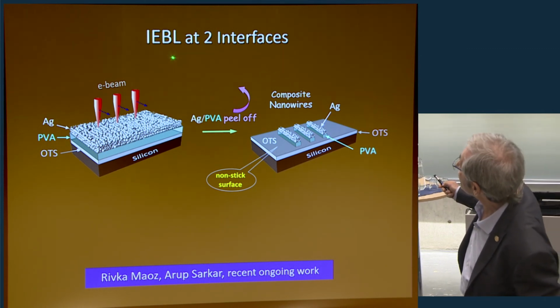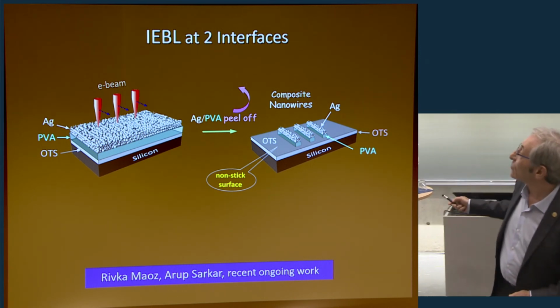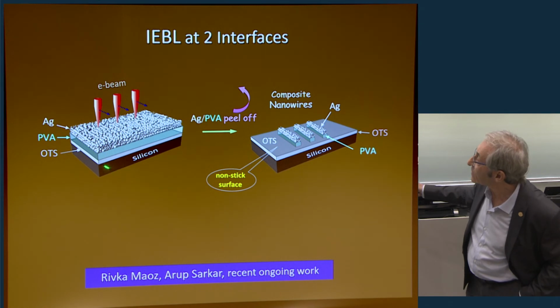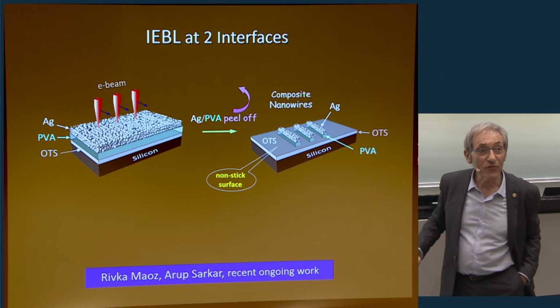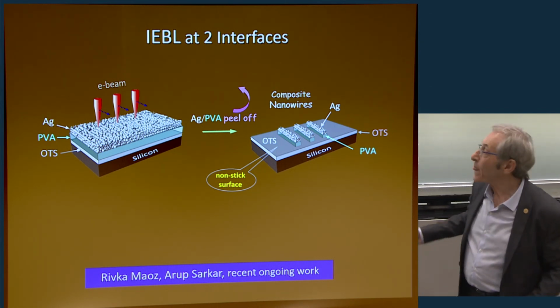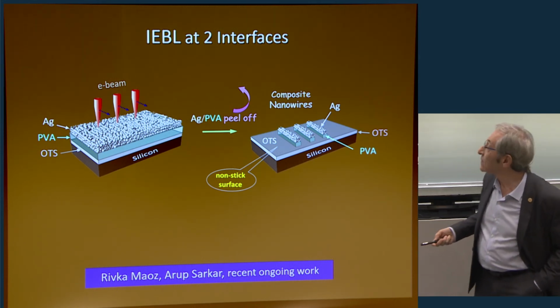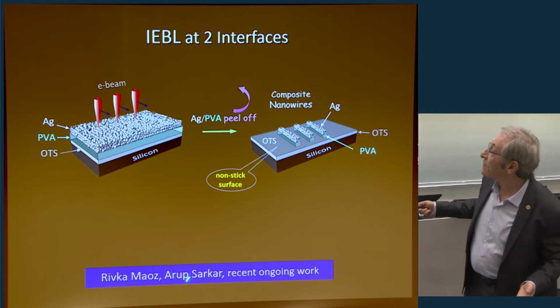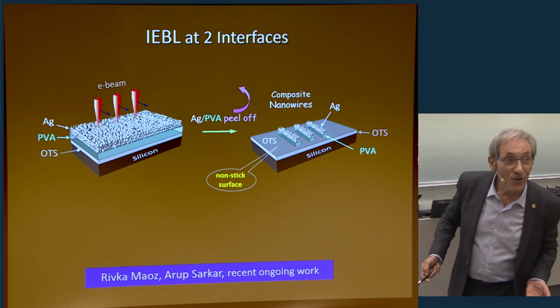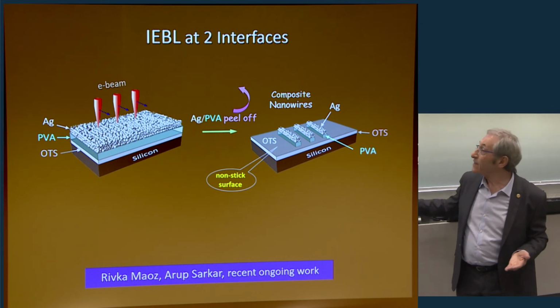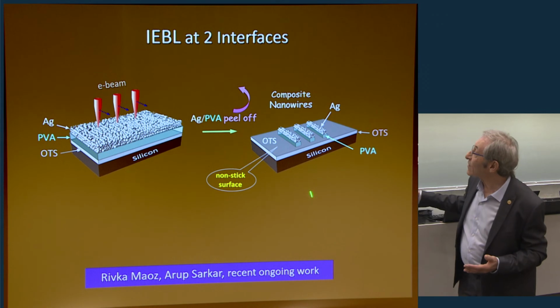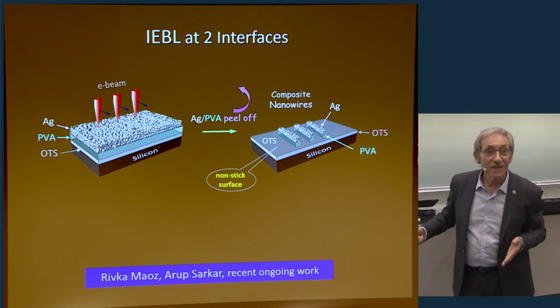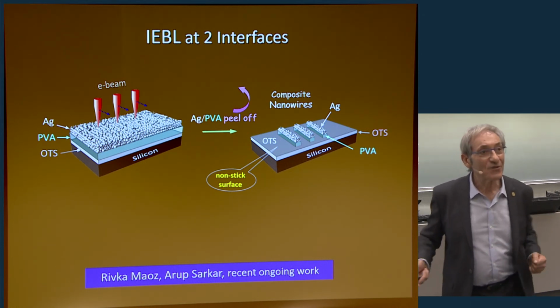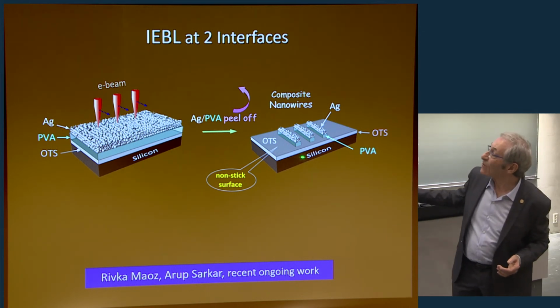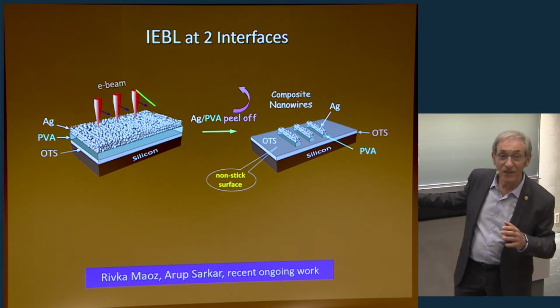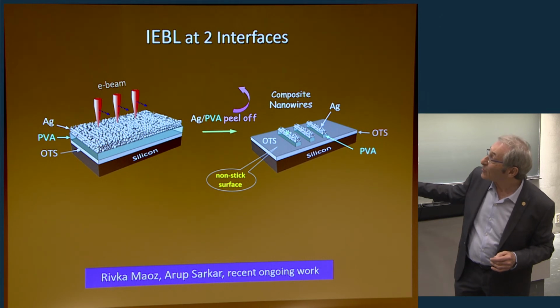So now we have interfacial electron beam lithography at 2 interfaces. We have here a sandwich: we have silicon wafer, we have the OTS monolayer, we have a thin layer of PVA. On top of this, we have a thin layer of evaporated silver. So that's the silver that we evaporate, we know it's silver, okay? And now we write with the electron beam, and then we peel off. Now, here is the good property of OTS, a non-stick surface. The PVA doesn't stick well, and the silver is evaporated on top of the PVA. So something remains on the surface only where the electron beam was used to write the pattern. And what is left on the surface is now PVA that sticks. So now we have a reaction at the interface between PVA and OTS, and between the silver and the PVA.